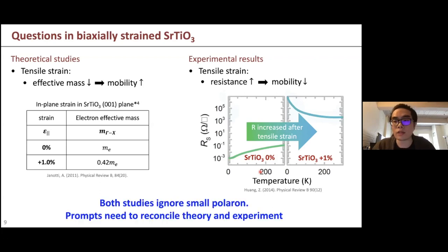Both studies did not consider the electron being a small polaron. So it is possible that the free electron effective mass does decrease when you apply tensile strain. However, if the small polaron gets stabilized more by tensile strain and becomes the dominating species of the electron, then you will not see how the free electron behaves in experiment. And I believe that's what they see in the experiment, because when you increase the concentration of small polarons, you decrease the conductivity of your thin film. So I believe that incorporating the small polaron in studying the strain effect is very important, rather than just looking at the free electron and how strain affects it.